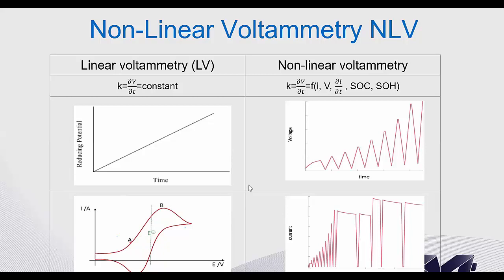Now, linear voltammetry is not able to fully charge a battery in 1 hour. I can tell you it's not possible. What we introduce here is a non-linear voltammetry, in which the slope, the voltage versus time, is not constant. It depends on many parameters, including the current, the voltage, the time derivative of the current, the state of charge, and the state of health of the battery. So we developed a protocol where, with this function, we can control at each time if this condition is met or not. If it is not met, we just go to current 0.